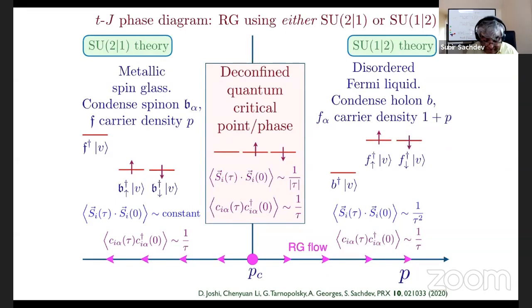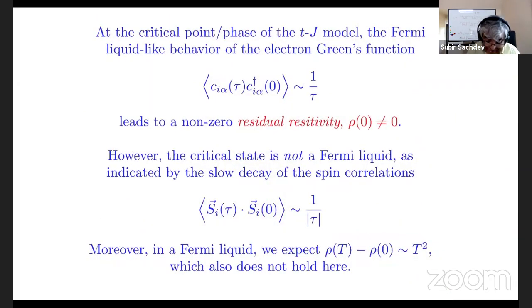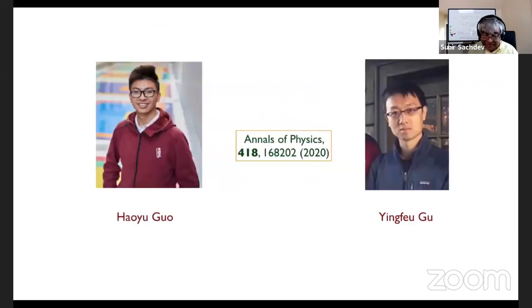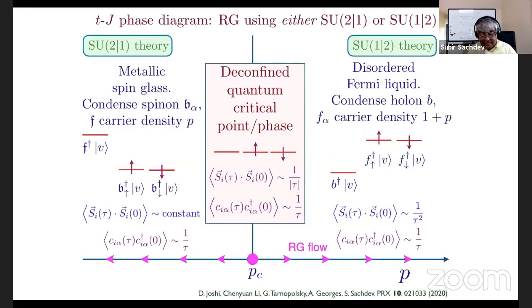Okay, and then in some ways the most interesting thing here, what about transport? So you can compute transport here and here relatively easily. Here you would conclude it's just a disordered Fermi liquid with carrier density 1 plus P with resistivity going as T squared. In this infinite dimension, you don't get these Altshuler-Aronov corrections, which will give you T to the 3/2 over here. And this is also a disordered Fermi liquid of some type, but the carrier density is small. But what about at this critical point?